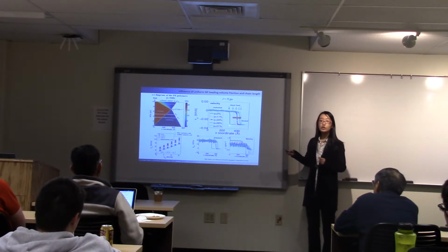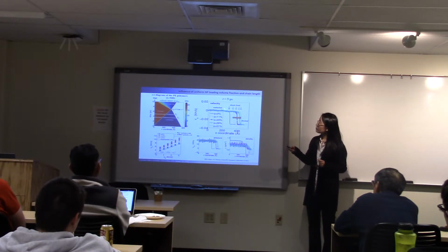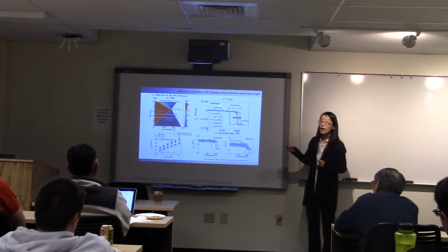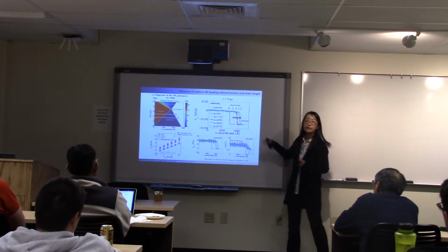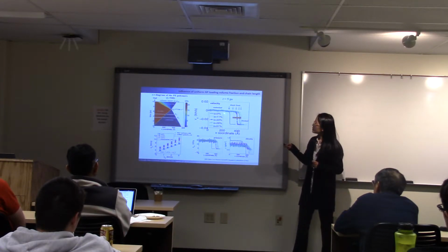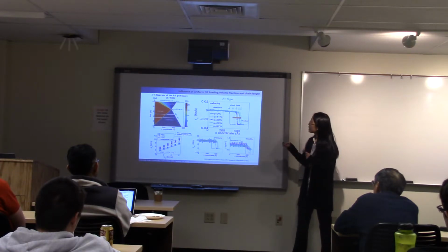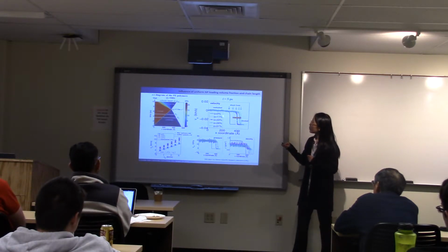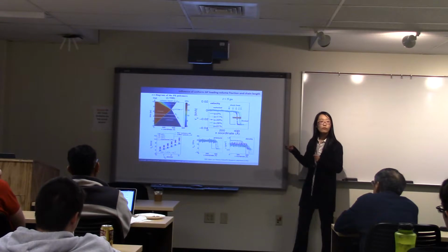Here is a snapshot. We can easily identify the shock front indicated by those arrows that separate the unshocked and shocked parts. This is the jump in the profile. And the different colors represent the different nanoparticle loading fractions. We can find that with increasing nanoparticle volume fraction, there's an increase of the shock wave propagation speed.